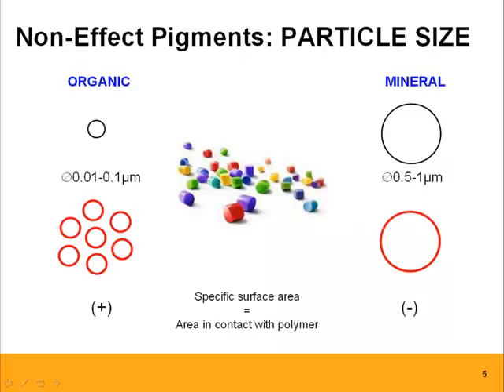So in regards to size, for the organic pigments, we have sizes between 0.01 and 0.1 micrometers, so very small. And if we want to mix, let's say, 1% of colorant into a polymer matrix, as you can imagine, we actually need a lot more pigment count on the organic side versus on the mineral side. So the specific surface area for organic pigments is actually a lot larger compared to the minerals. And that has an impact in regards to mixing and what kind of effort you have to take to really mix them well into the polymer matrix.